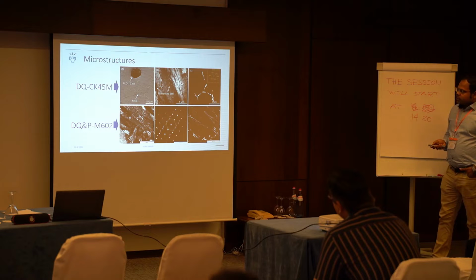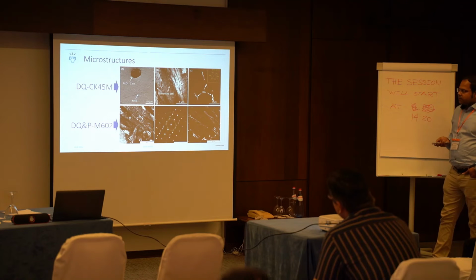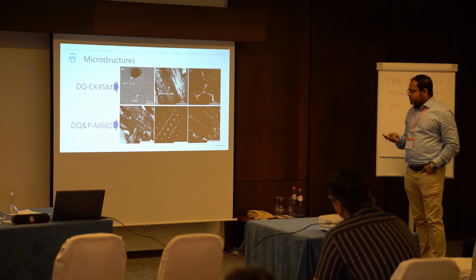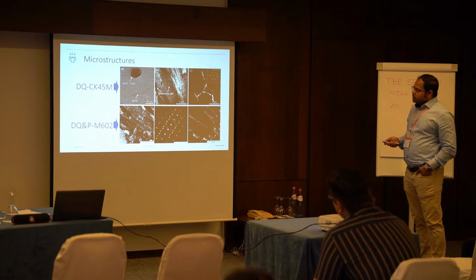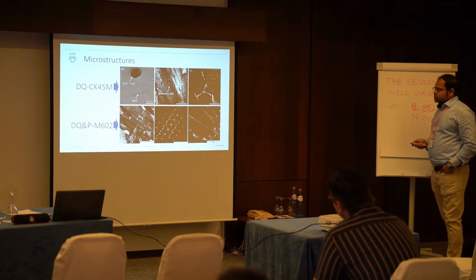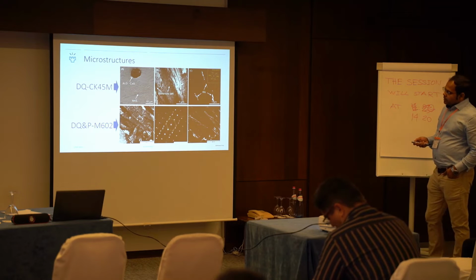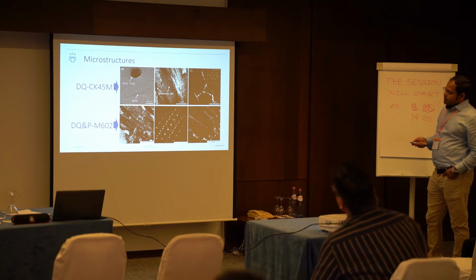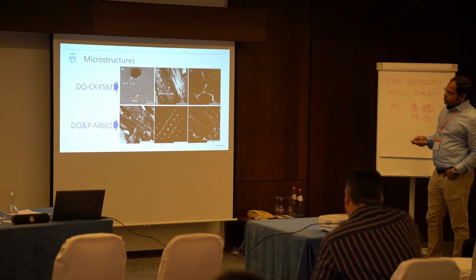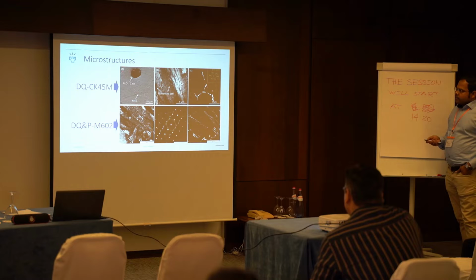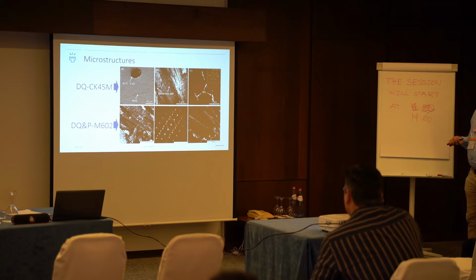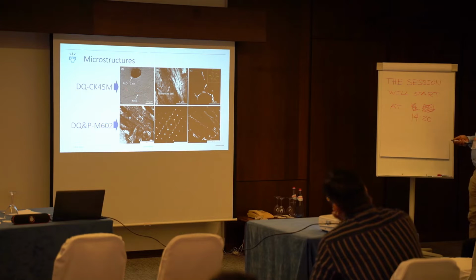And then the microstructure of CK45M steel mainly consists of a martensite matrix. Apart from this martensite, we observed 2 different types of inclusions. One is a slightly elongated shape and the other has a spherical-like structure. So based on EDS analysis, we confirm that this elongated shape inclusion is mainly manganese sulfide, whereas the spherical shape inclusion is mainly aluminum and calcium oxide. And as I said, this CK45M steel contains only a few fractions of retained austenite, so we can see that the film-like retained austenite mainly exists at the interlath boundaries.